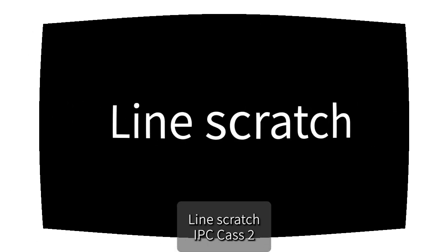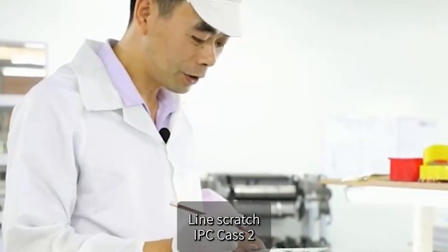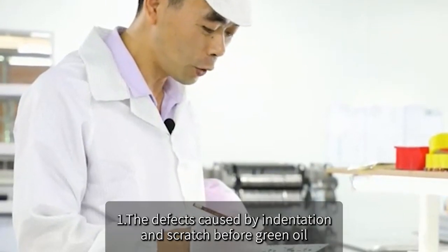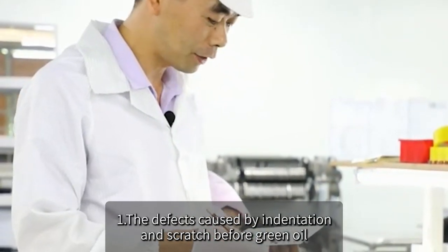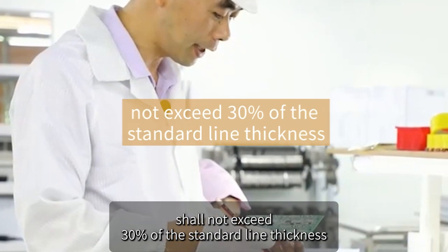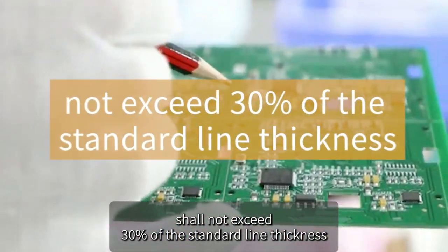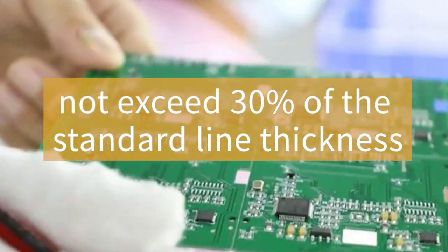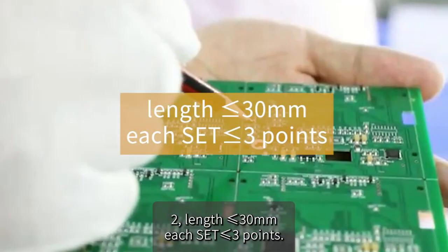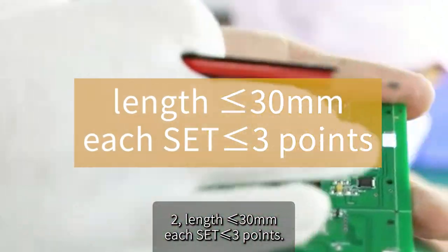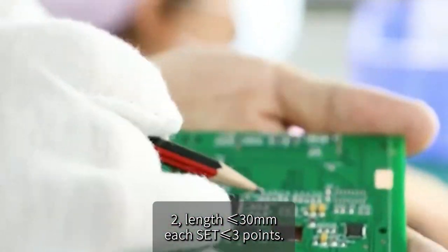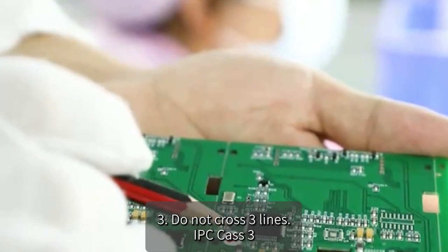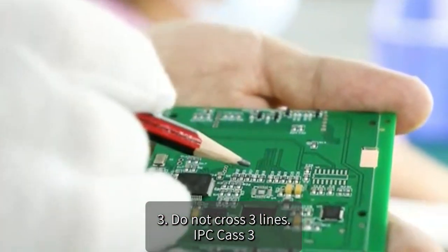Line scratch. IPC Class 2. 1. The defects caused by indentation and scratch before green oil shall not exceed 30% of the standard line thickness. 2. Length less than or equal to 30 mm, each set less than or equal to 3 points. 3. Do not cross 3 lines.